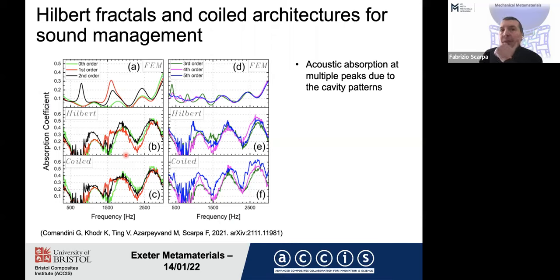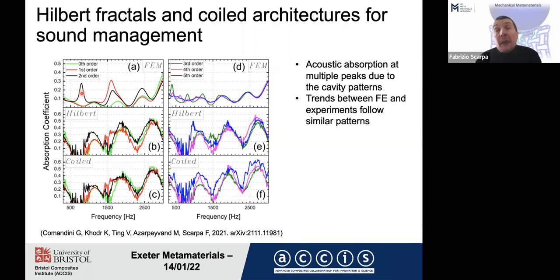Something that is interesting is if you look at the sound absorption simulated inside an impedance tube, there is no difference between the Hilbert fractal and the coiled architecture, which is not fractal. But again, the two architectures have the same length in terms of cavities. So what is important from a sound absorption point of view is the volume of the cavity, so the length of the cavity, especially the depth of the cavity itself. From the experimental point of view, you can see some differences, and that also depends on the specific setup of the impedance tube.